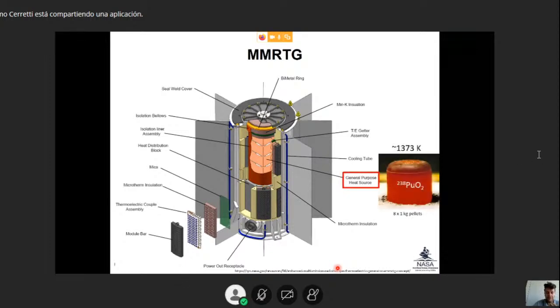So in the center here is where the GPHS, the general purpose heat source, are located. There are 8 pellets of plutonium dioxide, the isotope 238. The natural decay of this material generates heat, and that guarantees on the hot side of the thermoelectric module a temperature of about 1373 K, like 1100 Celsius. The cold side of the thermoelectric is kept at a temperature of about 473 K.